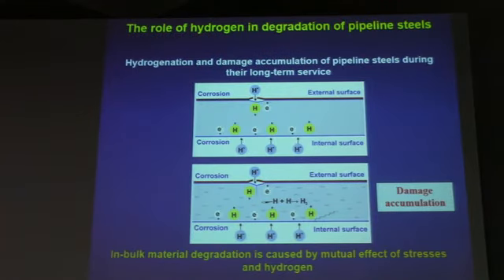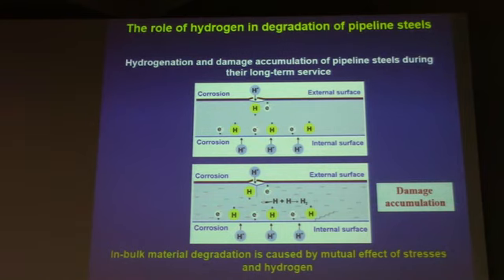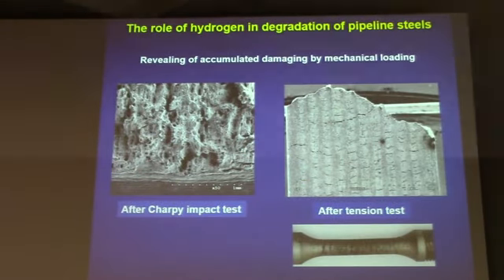What's more, corrosion is a key issue in the degradation of gas pipeline steels due to a destructive role of hydrogen absorbed by metal during corrosion. And the hydrogen charging a metal from inside and outside the pipe leads to a molecular hydrogen accumulation at certain cracking sites at nano and micro scales. And such circumstances promote formation, evolution, and accumulation of defects at nano and micro scales. And this is a main reason of a decrease of brittle fracture resistance of pipeline steels under operation. And here you can see some examples of revealing damage accumulation by mechanical loading.